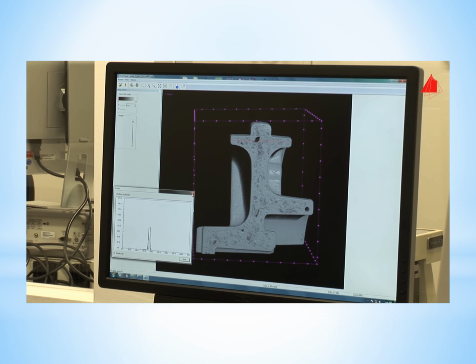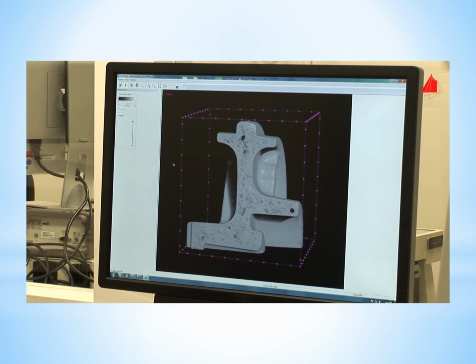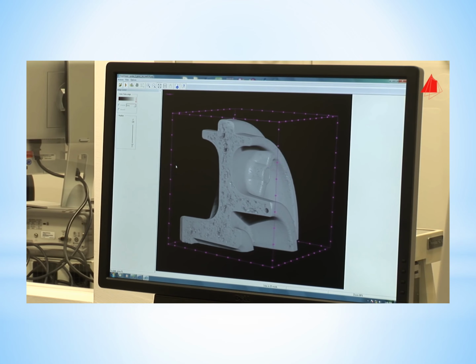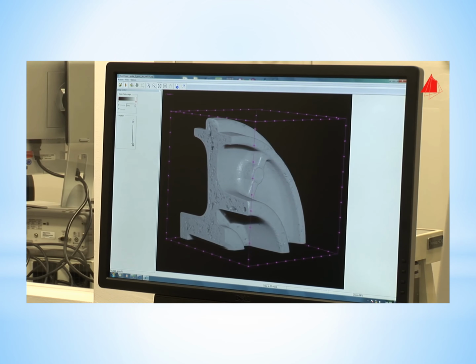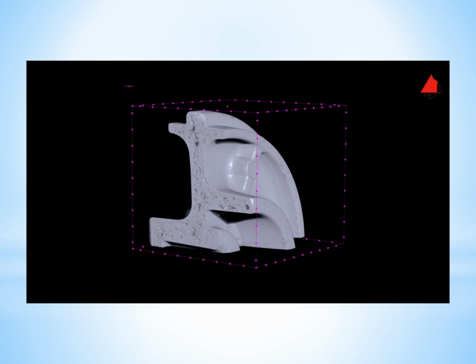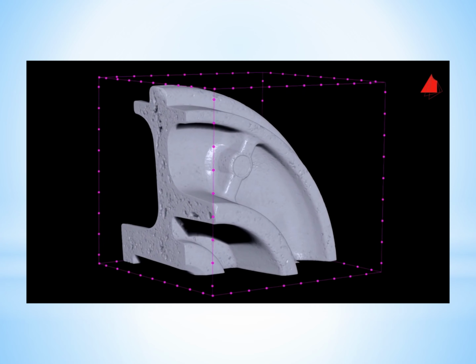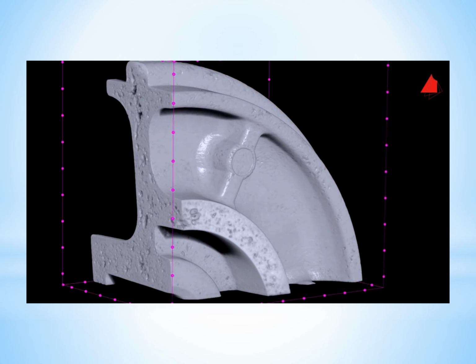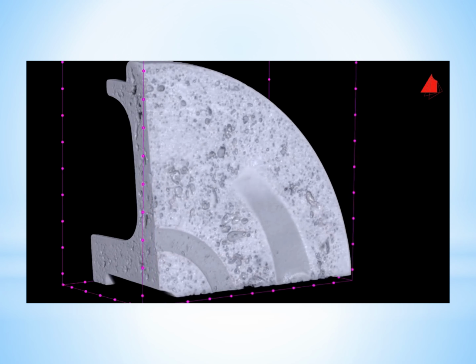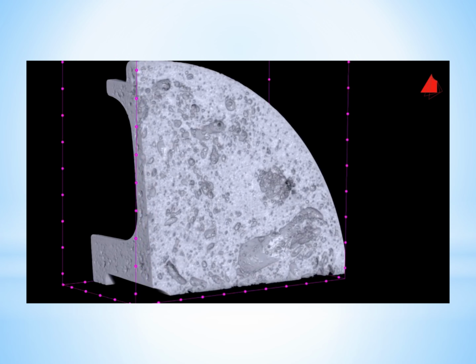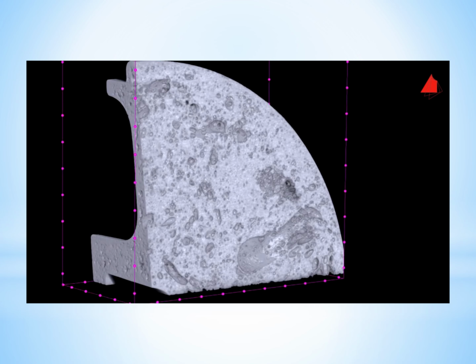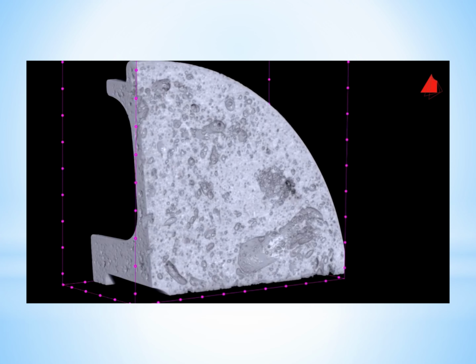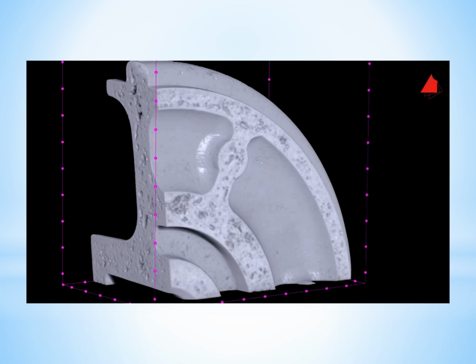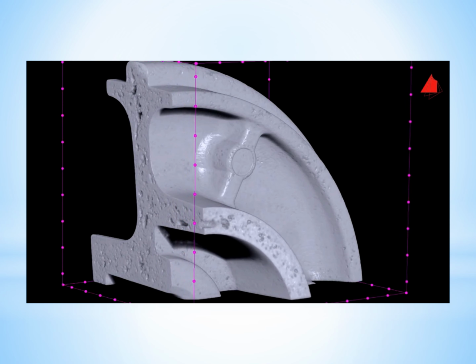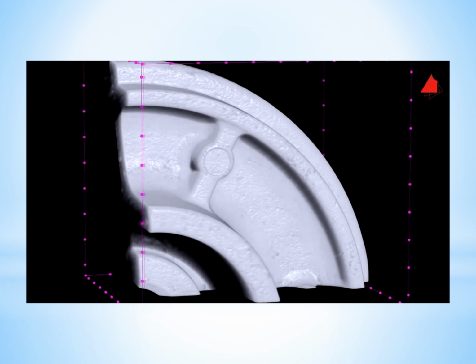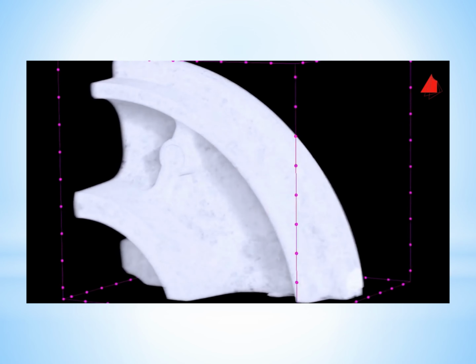The inside of the sample can now be inspected in detail, and above all, the method is completely non-destructive. Many pores of different sizes can be seen. The pores are filled with air that has been trapped in the course of the die casting process. The venting of the die has not been good and has led to a great number of large air inclusions. If preferred, the material can also be visualized transparently. Then the defect surfaces appear bright.